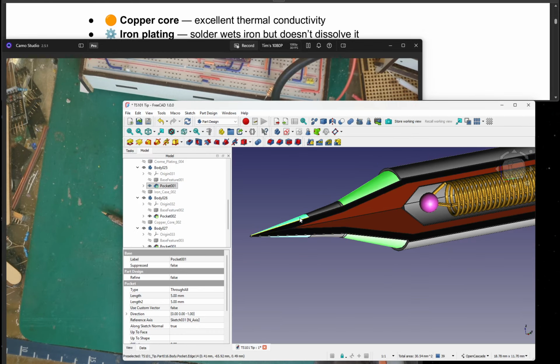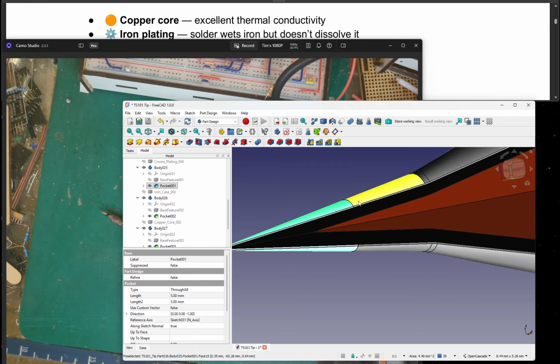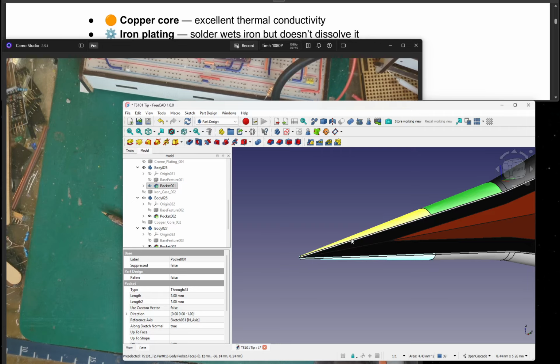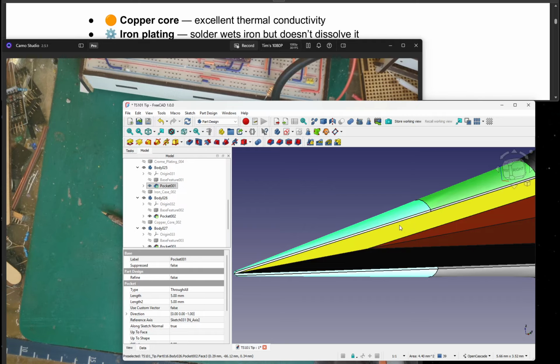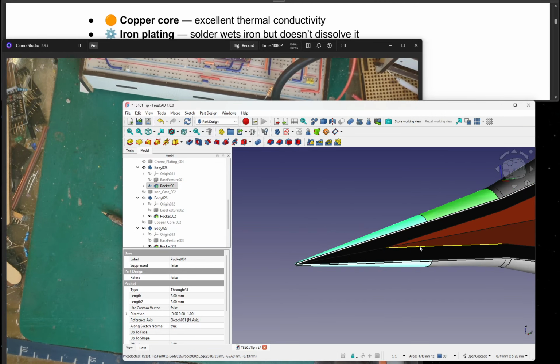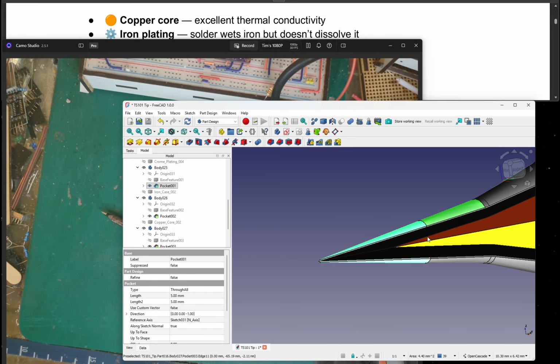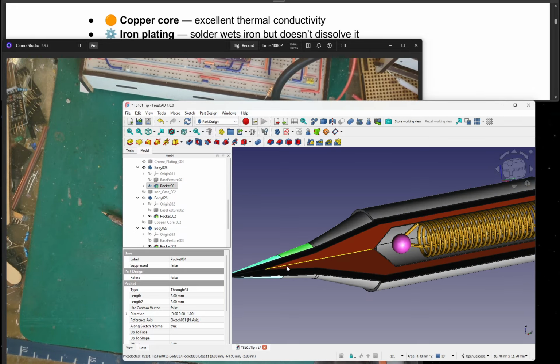But what we don't want is the chrome right to the tip, so the chrome stops about here, and it leaves the iron open to the solder, and solder will wet onto iron really easily, but the solder doesn't eat iron, so the tip doesn't get eaten away. And so this end bit here, you need to keep it tinned so that we don't get any oxidization of the iron to make it go rusty. Because if the iron end here goes rusty and you break through to the copper, then your tip is going to just disintegrate, because your tip will start eating away from the inside. So as long as you keep that tinned, that's going to be okay. They should actually come from the manufacturer already pre-tinned, so they don't oxidize.